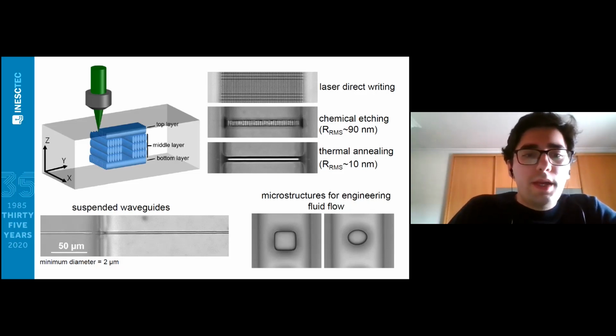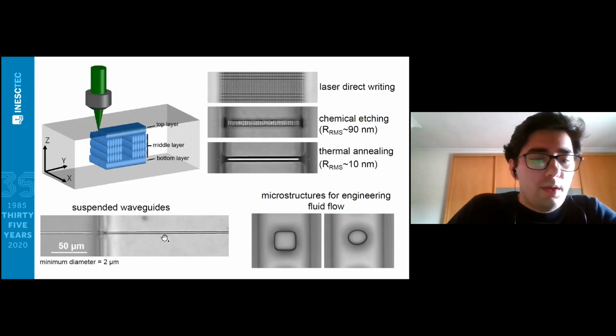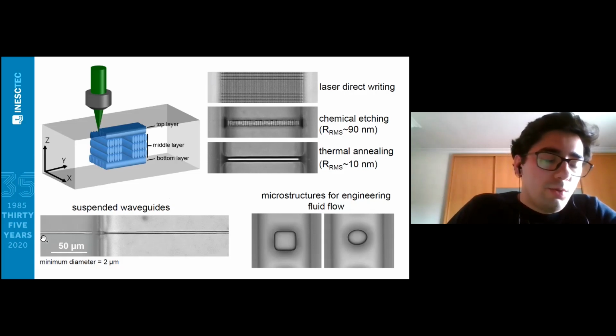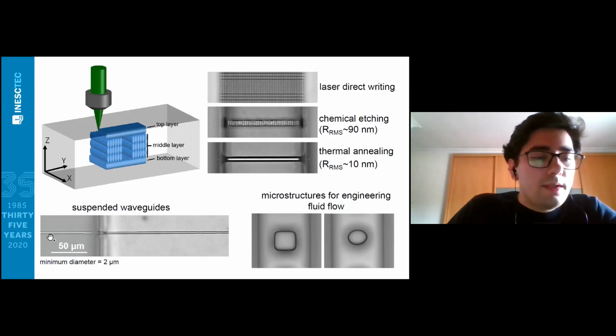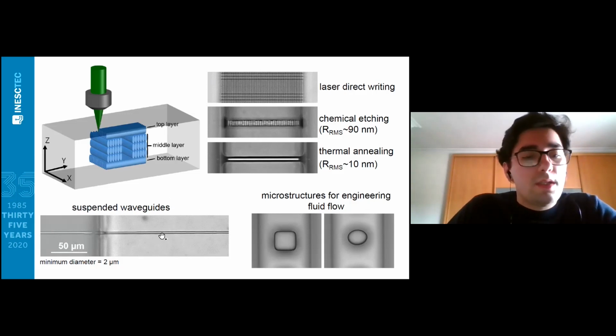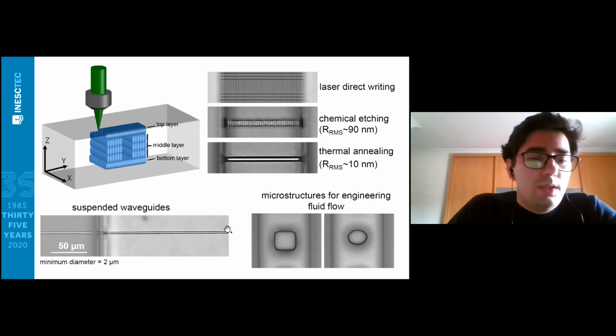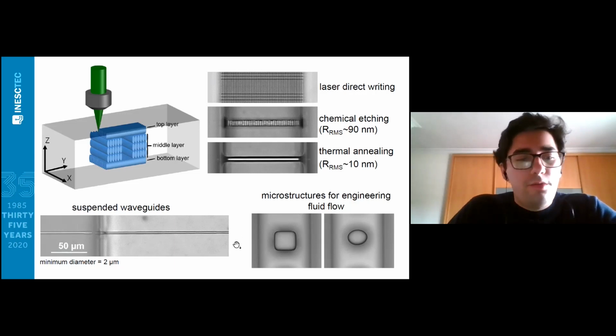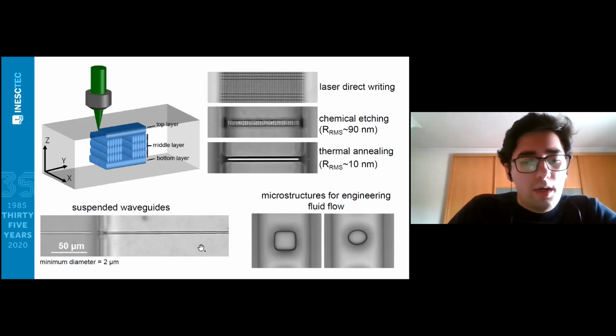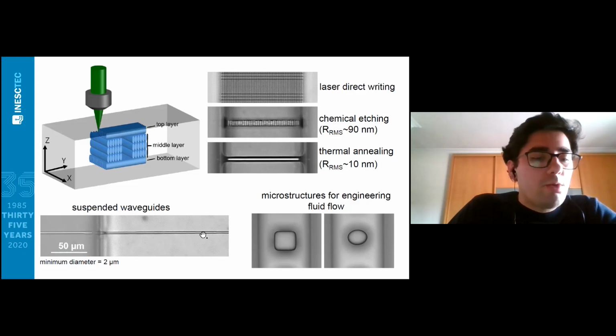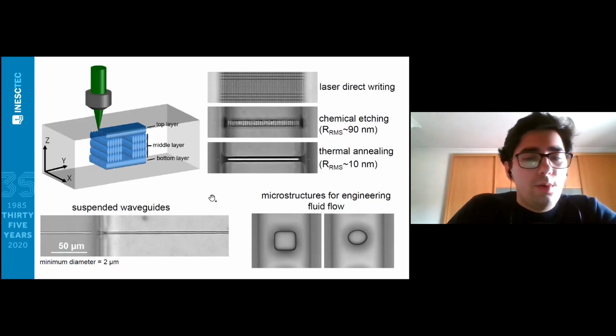So we can use these microstructures for different applications. For instance, here we have a suspended waveguide that is written within the microfluidic channel, and we also have a femtosecond laser written one that can be used to couple light to the suspended waveguide. Because the silica core has a higher refractive index than the surrounding medium, we can have waveguiding through this suspended waveguide. And by changing the refractive index of the medium inside the microfluidic channel, we can also reconfigure the properties of the waveguide. Additionally, we can fabricate waveguides with a diameter as low as 2 micrometers, which is pretty close to what you have with fibers fabricated through the heat and pull method.